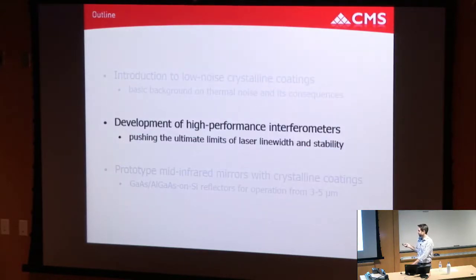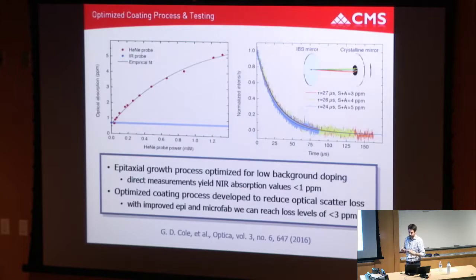I'll now go through the high performance interferometer, so really pushing the optical quality. That first prototype interferometer had a finesse of about 150,000 with relatively high losses. We've now worked very hard to push the absorption below 1 part per million. I wish I had an exciting scientific outcome for how we did that, but it just turned out: be careful, make sure the MBE chamber's clean, and then grow as fast as you can, because you're always going to have a flux of stuff in the background. So just get those layers down before that flux of stuff is incorporated into the structure.